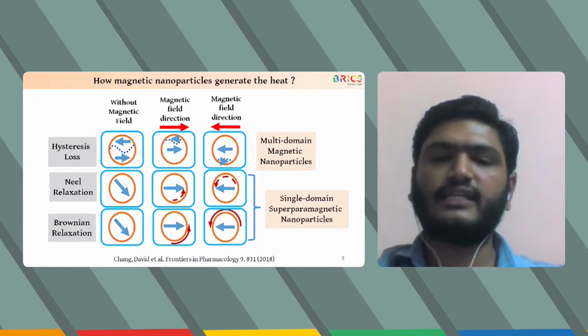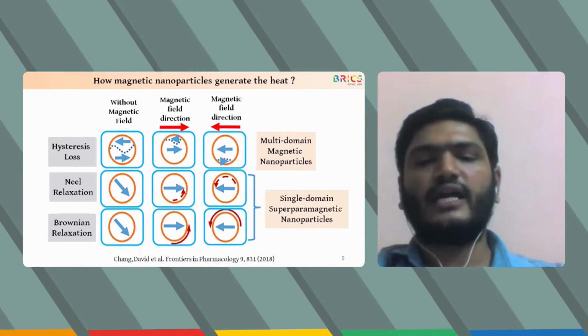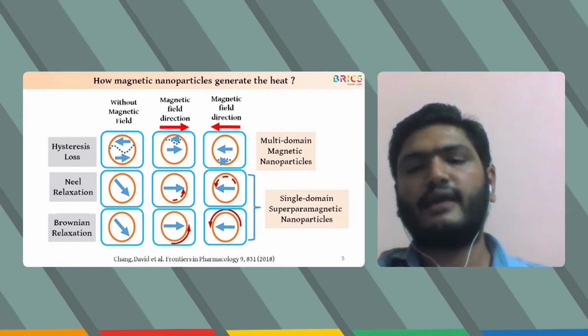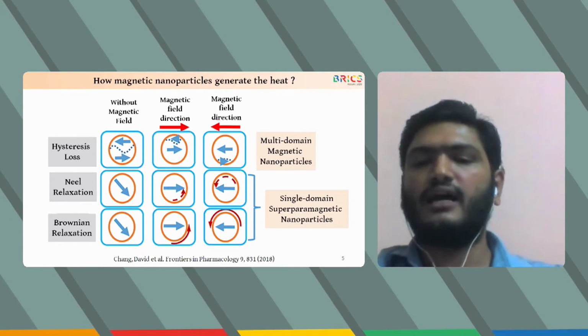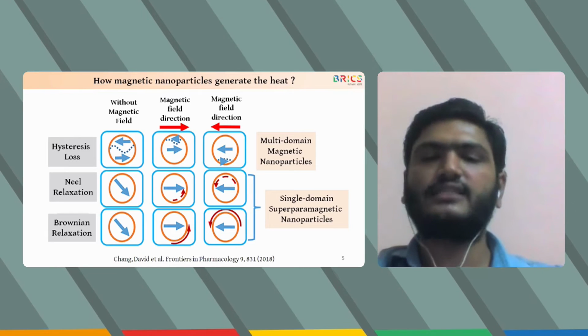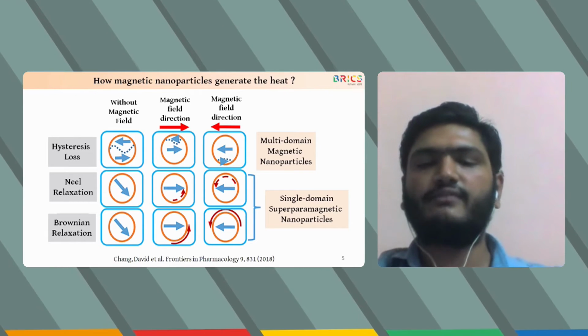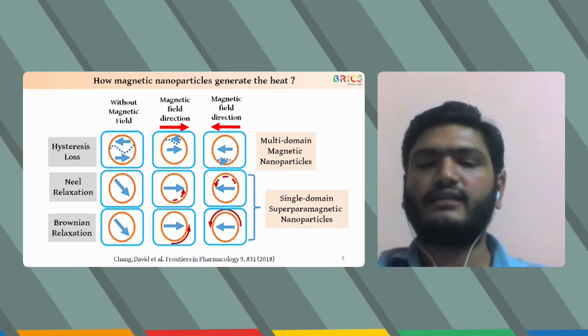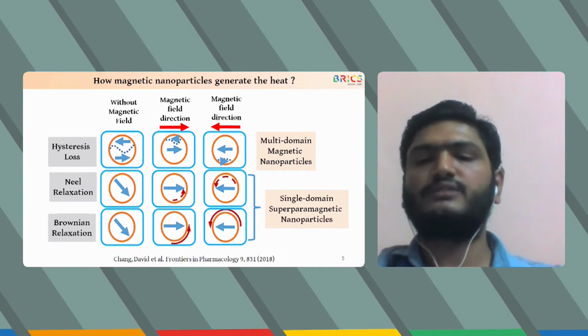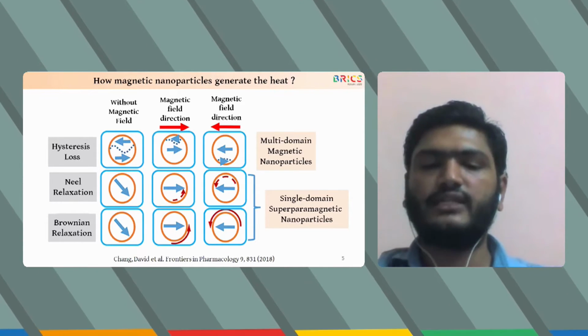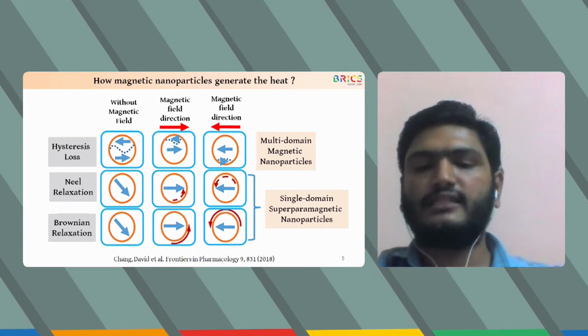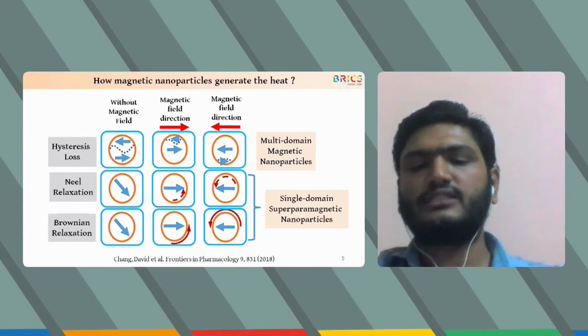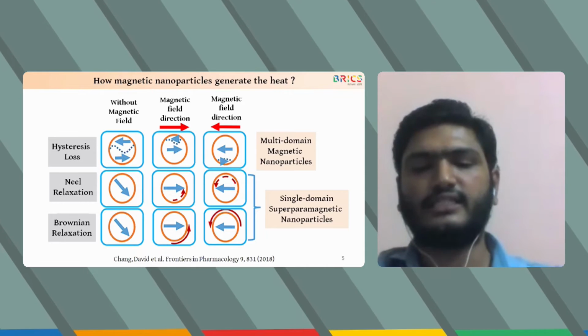You may raise the question of how these magnetic nanoparticles generate heat. As we all know, magnetic materials have a magnetic moment, and these magnetic moments on nanoparticles will align with the external magnetic field. As the external field changes direction, the magnetic moments also change direction. This produces dissipation leading to heating. There are mainly three losses which cause the heat: hysteresis loss, Néel relaxation, and Brownian relaxation.